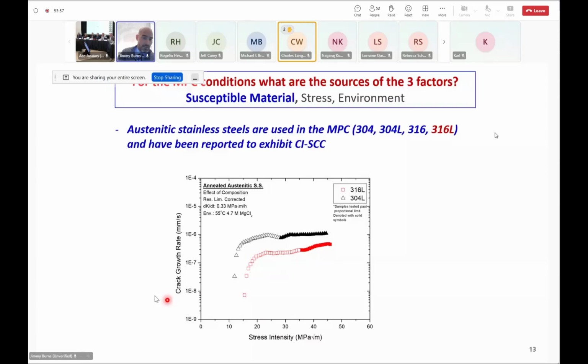This is a growth rate versus some mechanical driving force, and this just shows that we can get cracks to grow. As Jerry alluded to before, different materials have different levels of susceptibility, right? 304 is growing faster, and so that has a faster growth rate. And as he said, if you do have that stress and you do have that environment and they are sufficiently severe, you can get cracking. And if you do get cracking, then it cracks slower in 316 than it does in 304L.